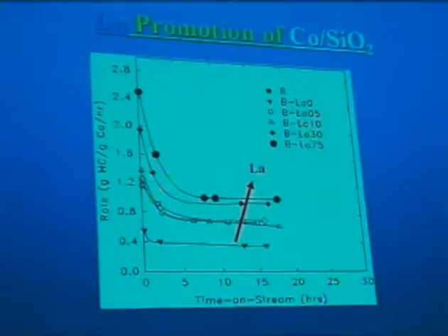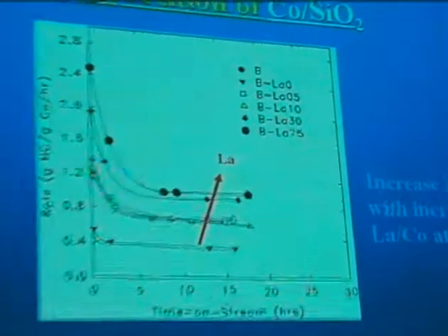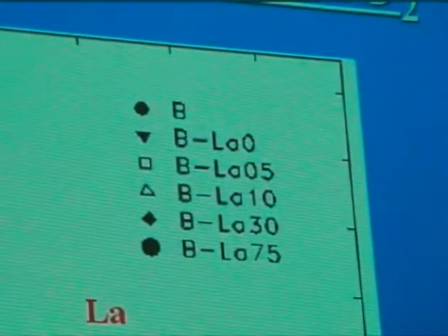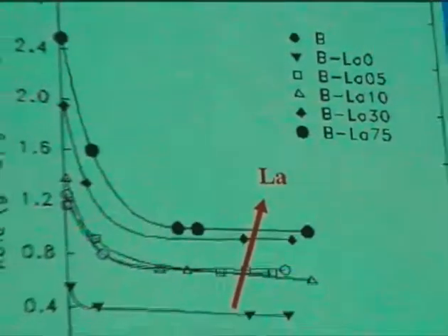Well, the other oxide that I mentioned is lanthanum, and you see this very often in patents. Of course, examples are usually given for lanthanum, and then everybody claims the whole lanthanide series, but that's the way you write patents, right? But in terms of lanthanum promotion, here is a cobalt on silica catalyst. And as you add lanthanum, you see a tremendous increase in the steady state rate. And in addition, in the case of the lanthanide series, you get improved chain growth.